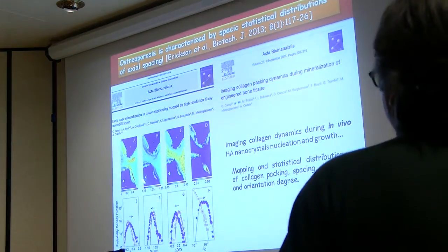At nanoscale, we can take the collagen fluctuation, or the distribution of hydroxyapatite nanocrystals, and that's the thing that gives the material its mechanical properties, because the bone is just a distribution of nanocrystals in a collagenous matrix. And this is important, for example, for preclinical applications in which a particular distribution of spacing of the collagenous matrix can be associated to osteoporosis or other pathologies.